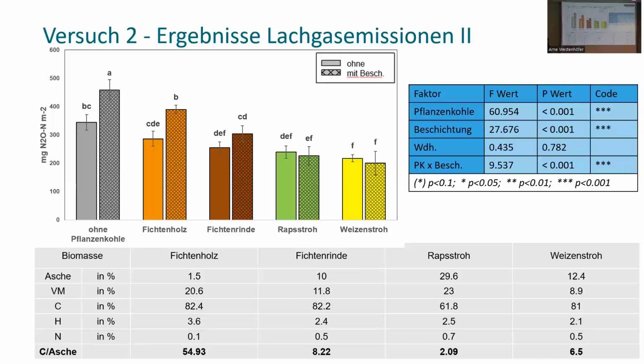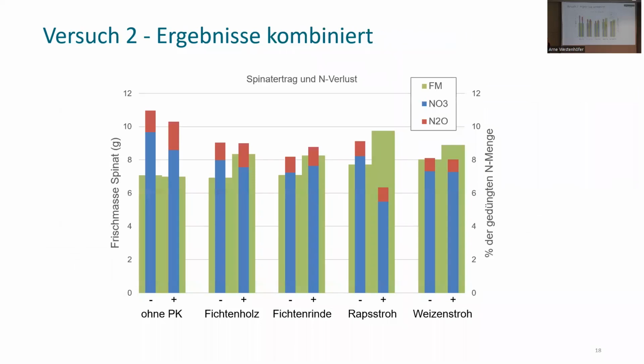And if you look at the ratio between carbon and ash, you see that the candidates on the other side here and the variant with rape straw and corn and wheat straw have a low ratio combined with ash and organic coating. Obviously, there are complexes at the biochar surface that have the nitrate retention capacity and can explain the increased growth of the plant.